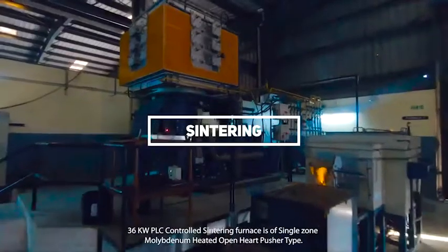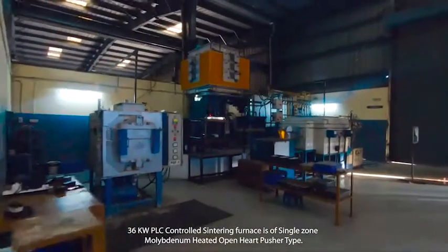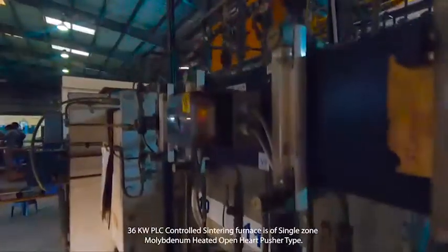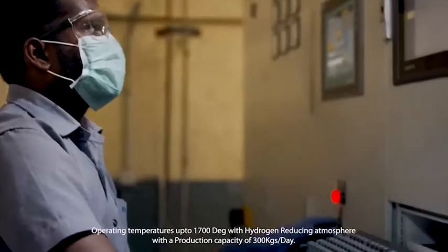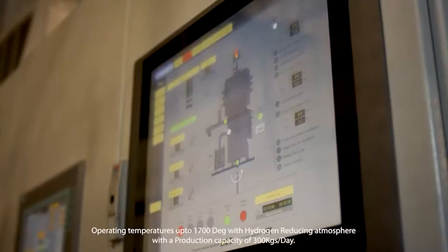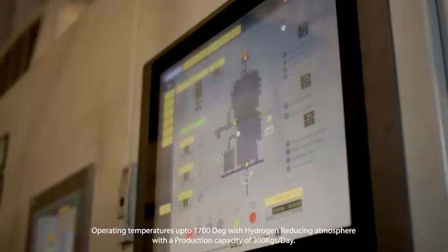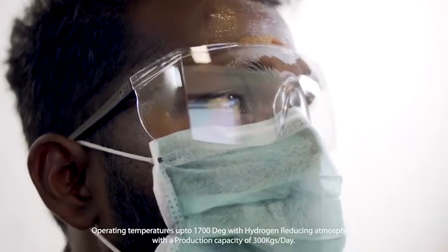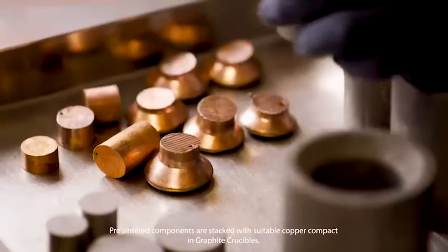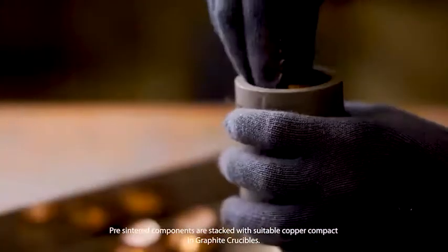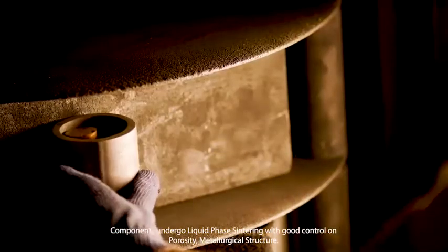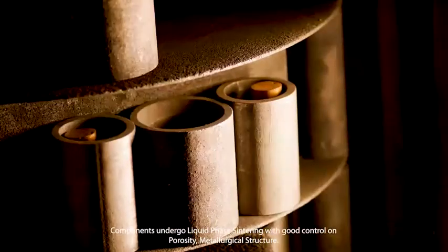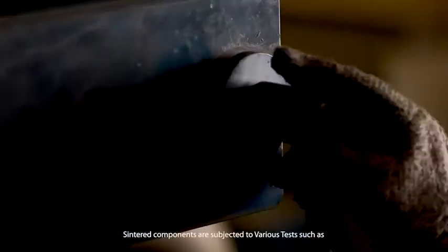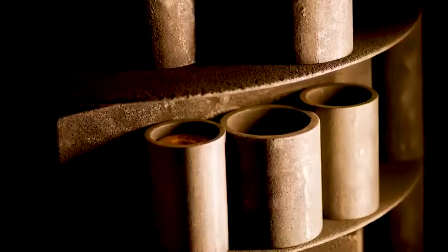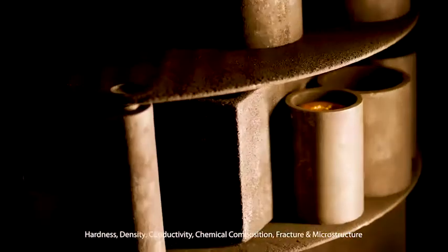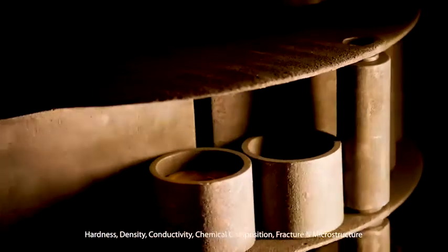Sintering. 36 kilowatt PLC controlled sintering furnace is of single zone molybdenum heated open hearth pusher type. Operating temperatures up to 1700 degrees with hydrogen reducing atmosphere with a production capacity of 300 kilograms per day. Pre-sintered components are stacked with suitable copper compact in graphite crucibles. Components undergo liquid phase sintering with good control on porosity, metallurgical structure. Sintered components are subjected to various tests such as hardness, density, conductivity, chemical composition, fracture and microstructure.